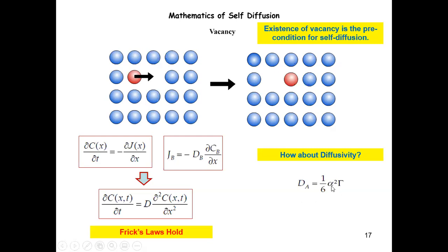And we also see that this geometrical parameter, which tells you the interatomic distance, we can easily change to whatever the lattice we're working on, right? The key thing that absorbs all of the things that we need to work with is this hopping rate, right? Because the mechanism by which an interstitial particle hops into a neighboring site, and the mechanism by which a substitutional particle hops into a neighboring site, is different, right? In the substitutional case, we have to wait for a vacancy. So we'll probably see that's where the difference comes from.